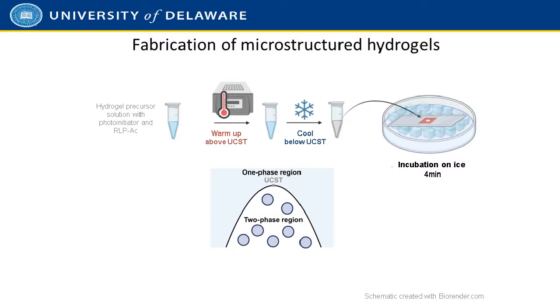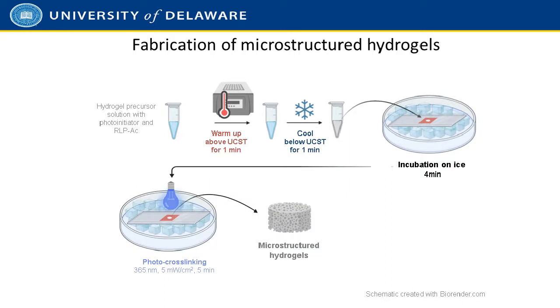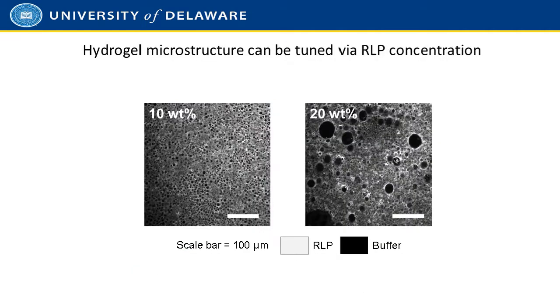So when we want to induce phase separation, what we do is make a solution of the RLPs, warm the solution up so it's in the one phase region of the phase separation diagram, and then we can cool the solution below the UCST, introducing a phase separation. We've done that by easily incubating these materials on ice, but you can also incorporate it in a plate reader or some other form of temperature control. The gels are then illuminated by UV light, and then the gels can be easily collected from these synthetic protocols to make microstructured gels. We know that the microstructured gels can be made to have open domains that are on the length scale relevant for cells.